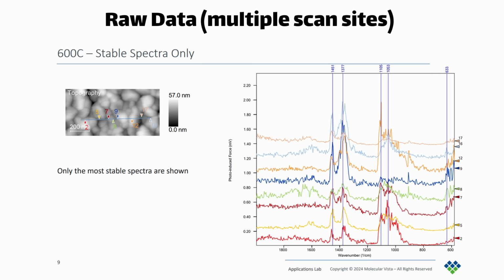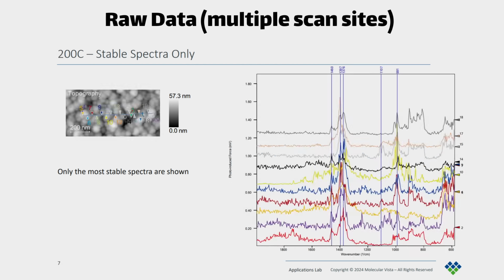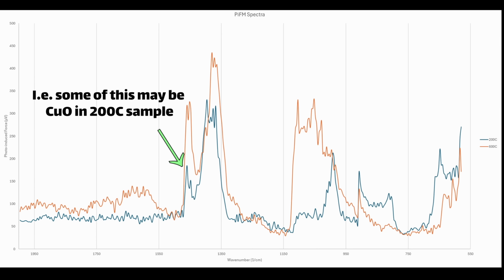I'm still working with Molecular Vista to refine these results. They've actually requested some calibration samples from a collaborating university, so that we'll have some spectra from a real university lab to compare against. I don't think the results will change much, but it might let us differentiate how much of each oxide is present in the samples. It's likely that both samples are actually a mix of the two oxides to varying degrees.